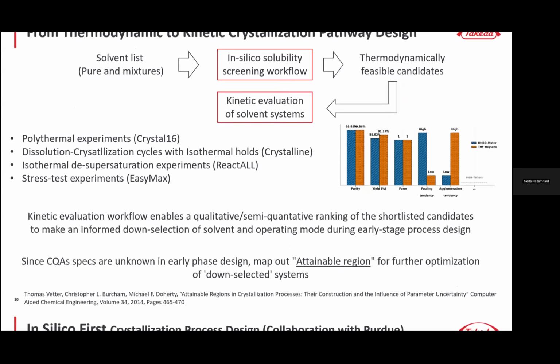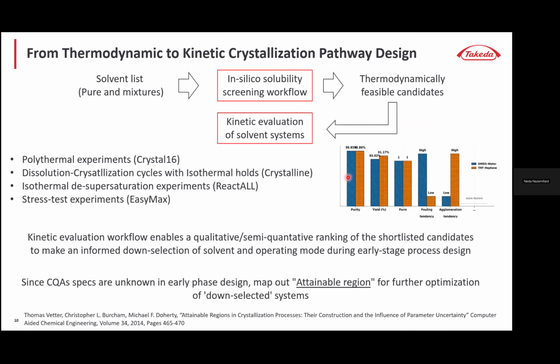So here, again, you can see that for the same compound A that I showed you, we used solubility screening, or in silico screening, for narrowing down to a couple of solvent systems. We are looking at DMSO water, which was selected from the solubility screen, and the other one, which showed a good yield and slurry concentration, was THF heptane, for instance. So we ran these experiments.